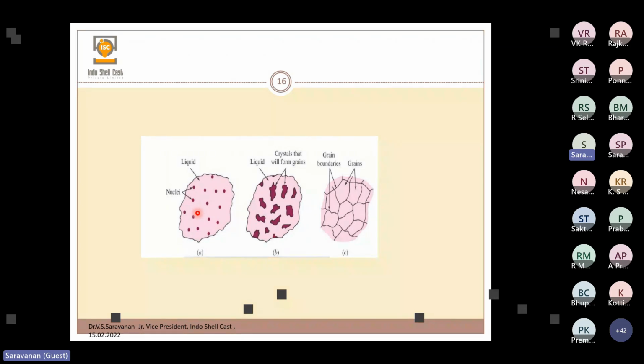because you have studied these things in our schools and colleges, the ionic bond, covalent bond, so many things. Whenever the atoms come close to each other, they will bind each other, and then it is creating the solid phase. So here, more nuclei will form, and then slowly the nuclei will group together and grow as a dendrite. The dendrite will grow, and then finally it will become a solid, and then we can see the grain boundaries also. So here our point is where the nucleation starts, at what temperature, and how many nuclei are created inside the metal, whether it is sufficient to continue the further solidification process. So these things are very important.